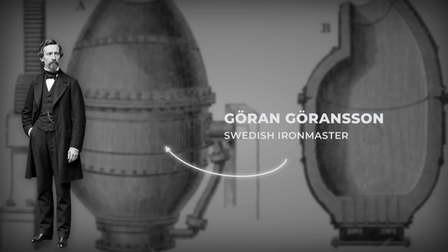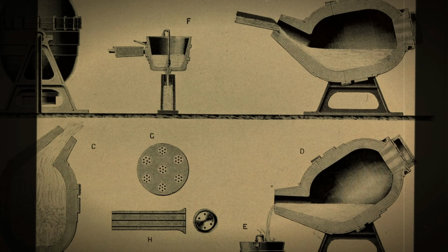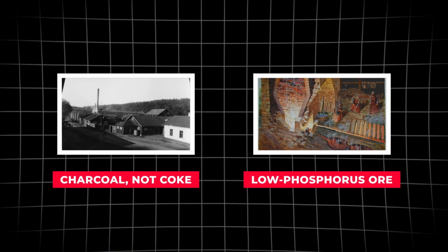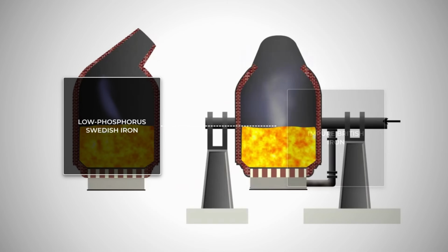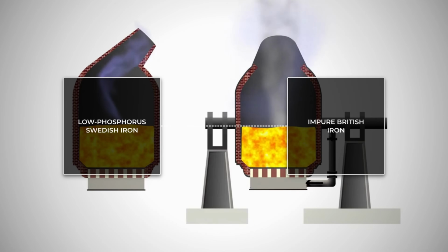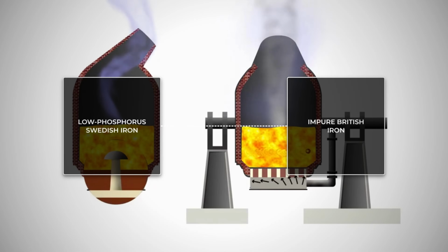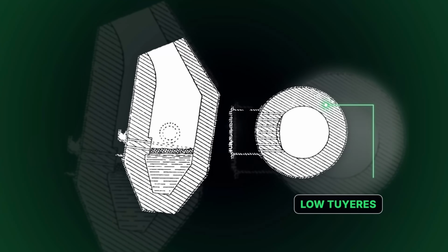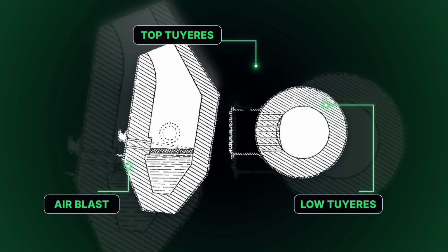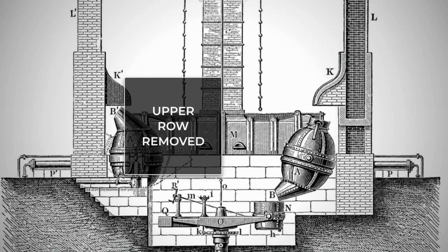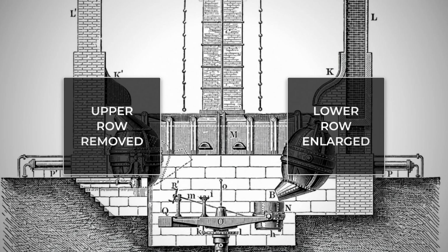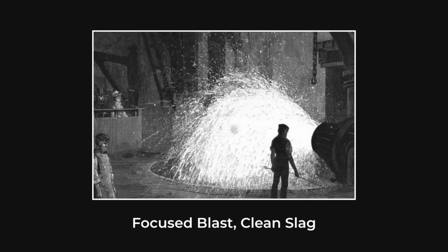Göransson had worked out 2 things his English counterparts had missed. The first was chemistry. Swedish pig iron was smelted with charcoal rather than coke, and Swedish ores were low in phosphorus, which meant the raw material was clean in a way British iron simply was not. The second was airflow. The Bessemer converter fed its air blast through tuyeres, the nozzles set into the bottom of the vessel. Göransson had the upper row of tuyeres removed entirely and enlarged the ones in the lower row, then pushed the blast harder and hotter. The theory was that a stronger, more concentrated blast would keep the bath hot enough for the slag to separate cleanly instead of getting trapped in the metal as it cooled.